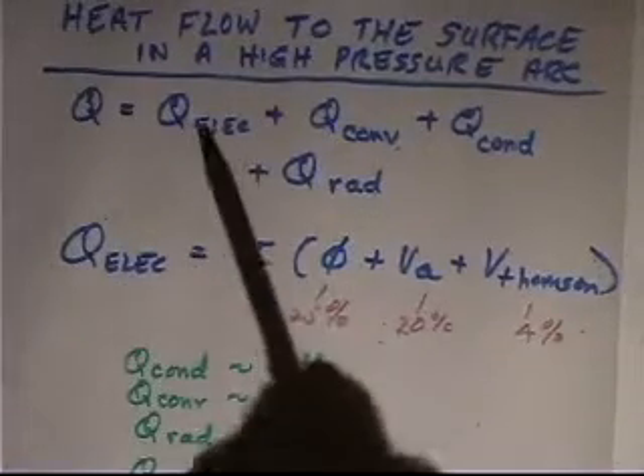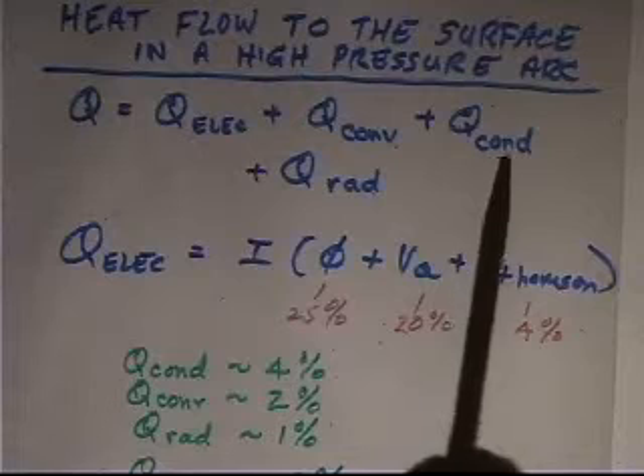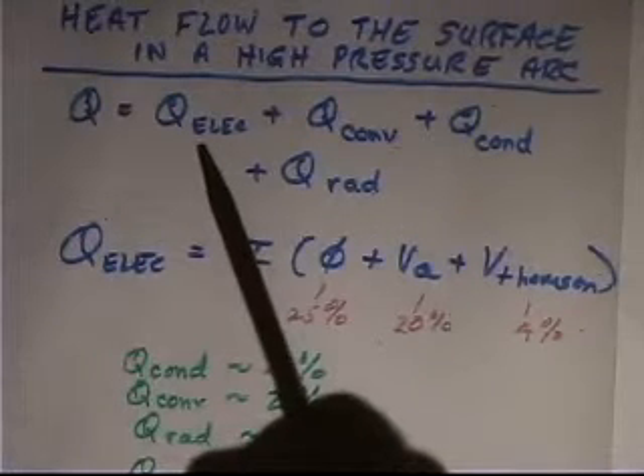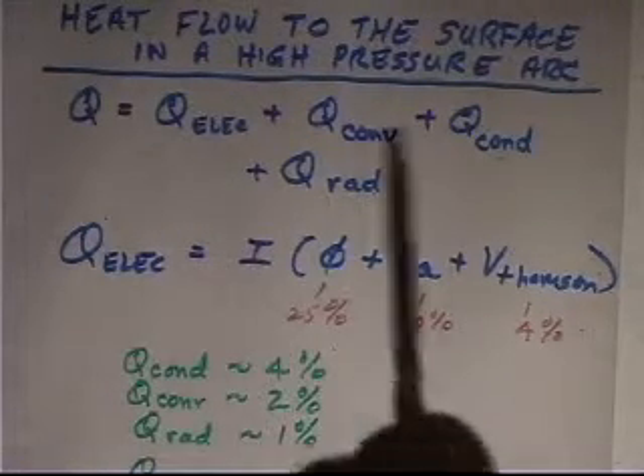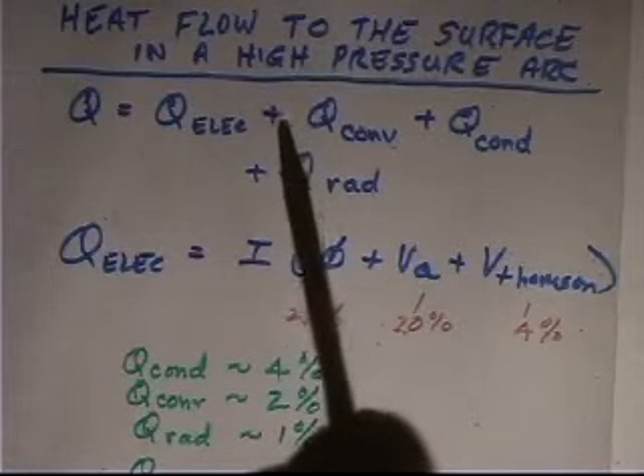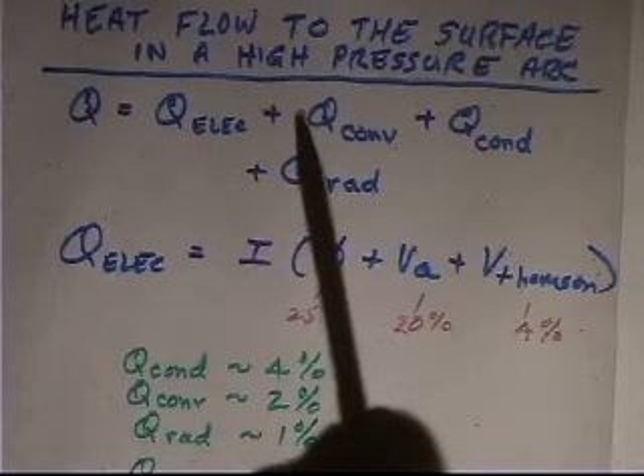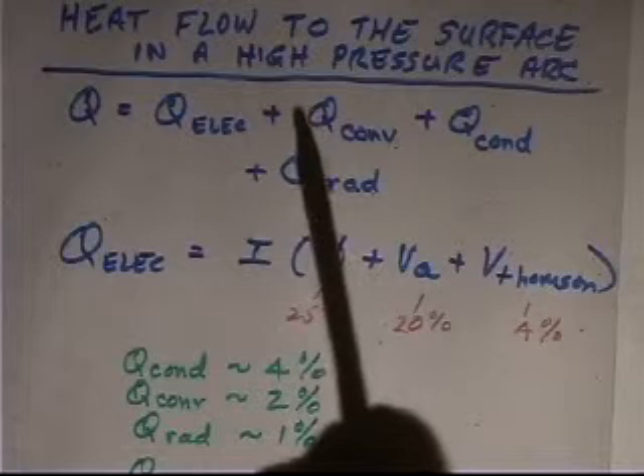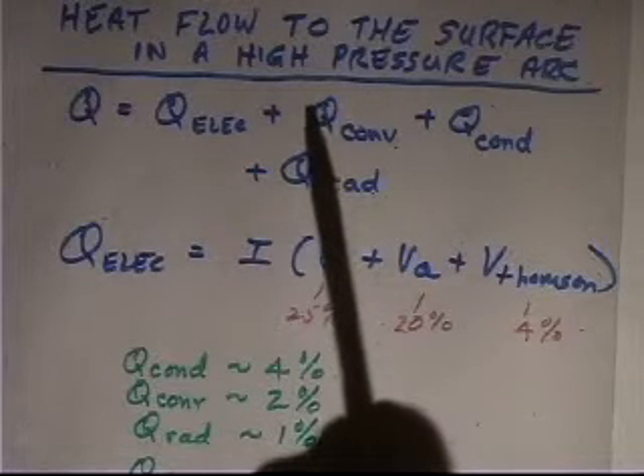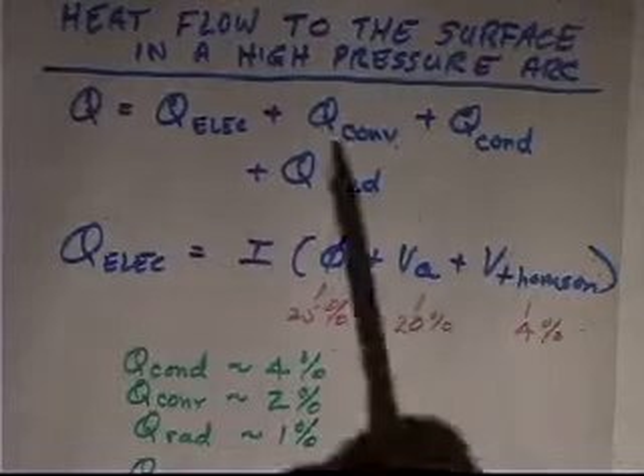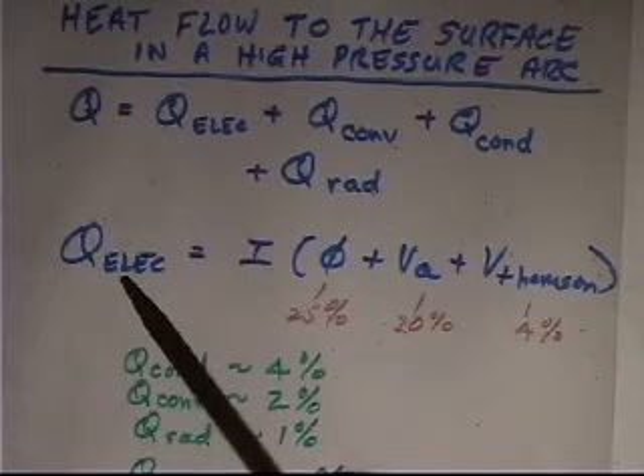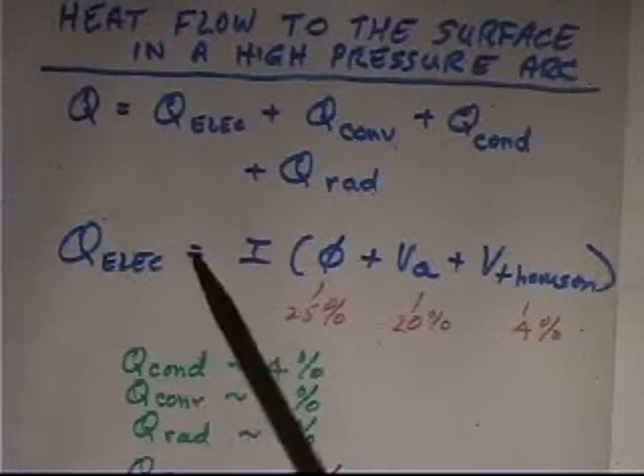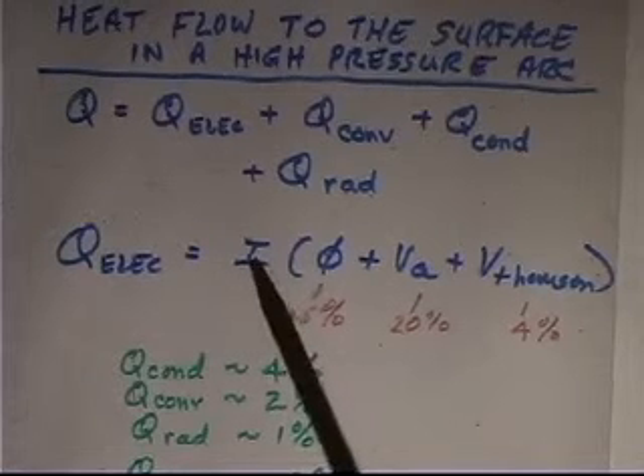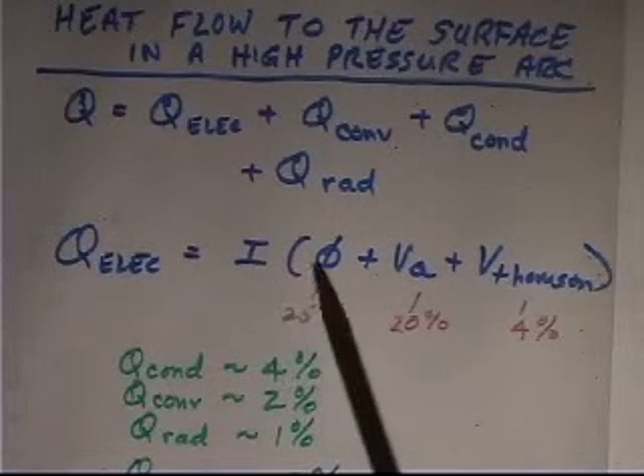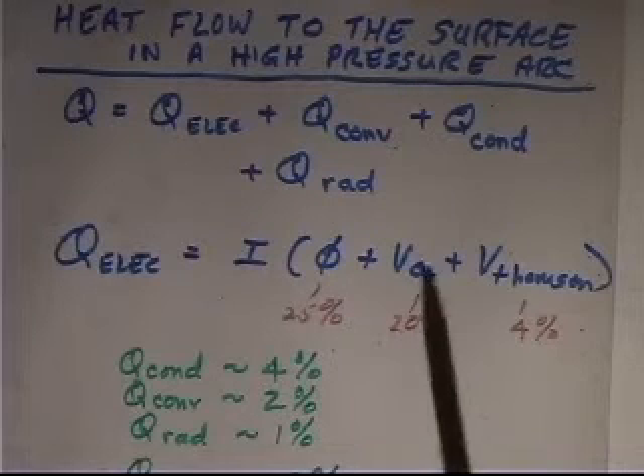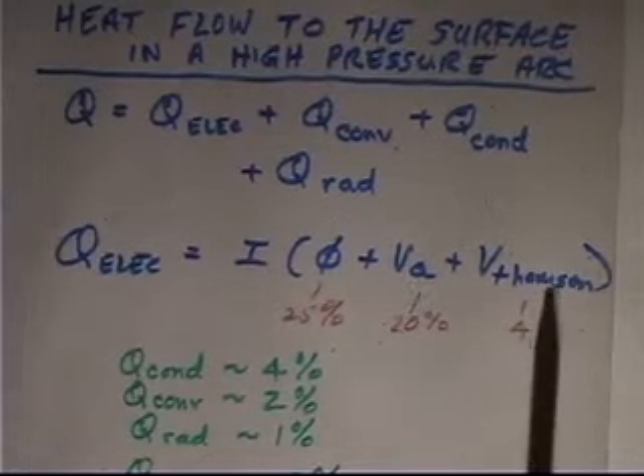But the interesting thing here is it turns out that 80 to 90% of the total heat in the arc comes from the electron flow. It turns out the arc itself is only about 50 to 60% efficient. A lot of the heat is just going off as hot gases in the atmosphere. But about 50 to 60% of the heat actually gets into the workpiece from an electric arc. And the electron flow creates heat by the following mechanism. It's the current in the arc times the work function voltage, the anode voltage drop, and the Thomson voltage.